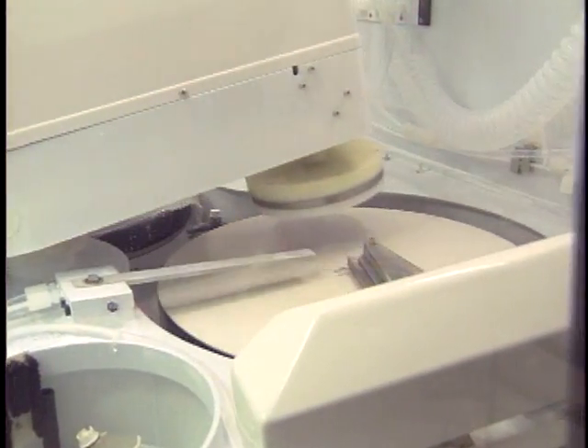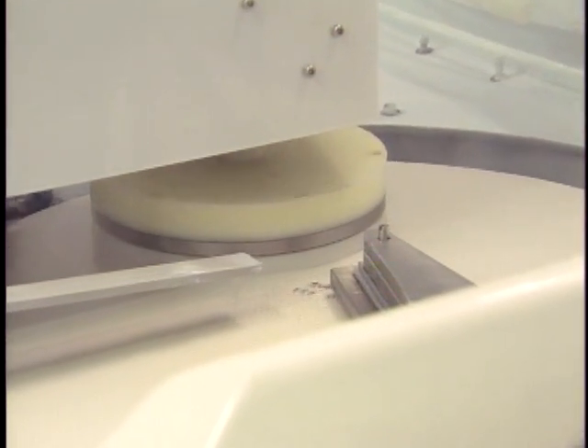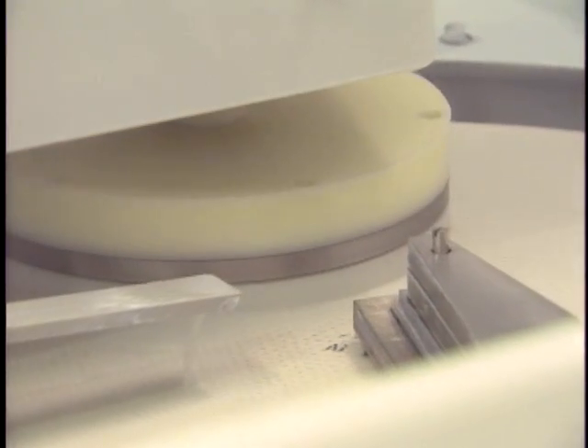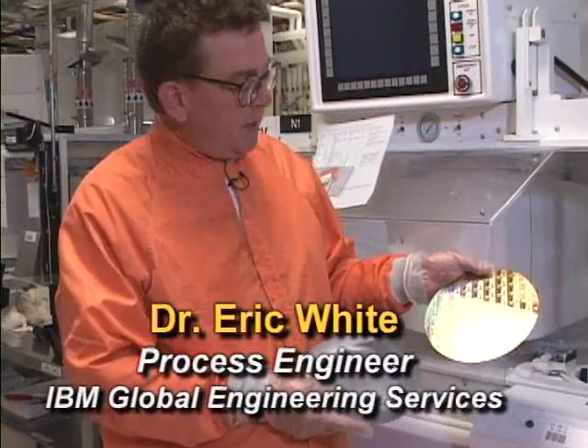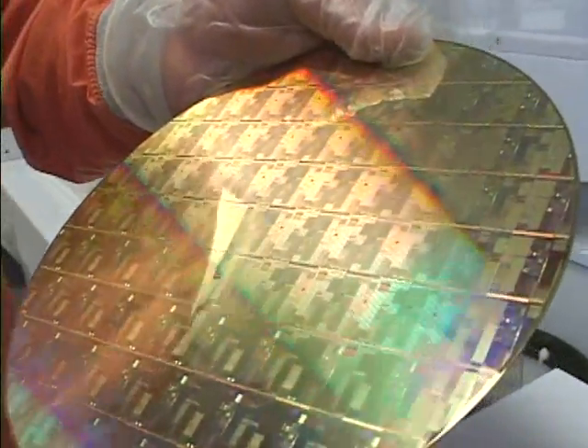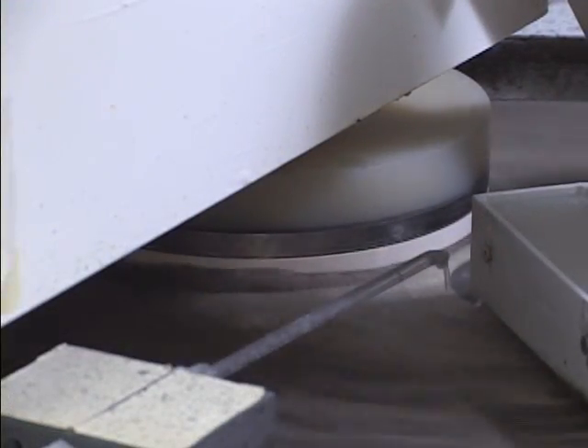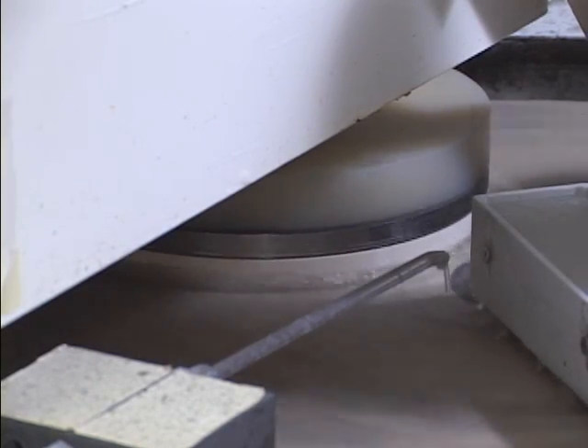The innovative process involves effectively erasing the chip circuit patterns from the wafers. The way we process these is we have a wafer like this, which has been scrapped in the line. You can see it has a pattern on it, so it's a customer wafer. We take this wafer and we use a polish tool, like the tool behind us, with an abrasive pad and deionized water. And with the parameters we've developed, we can remove the pattern entirely without damaging the silicon underneath.